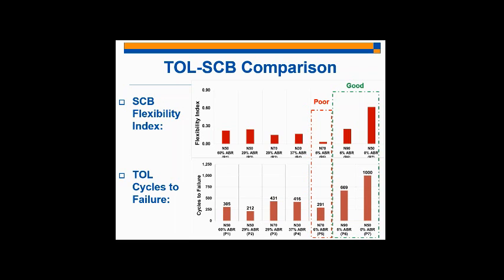Do the rankings of the performance remain similar to that of the test when conducted at -12? That assumption would require that low temperature testing conditions are appropriate. You are investigating a temperature dependent viscoelastic material. When you're looking at low temperature failure or fracture, the rate we're using is 0.7 millimeters per minute, which is significantly faster than what I would say happens in the field. So it is low temperature, but precisely because this is a viscoelastic material, the rate you're testing at really matters, as well as the temperature. Just because I'm testing at low temperature doesn't mean I'm accurately portraying what's happening in the field. My rate is also very important.